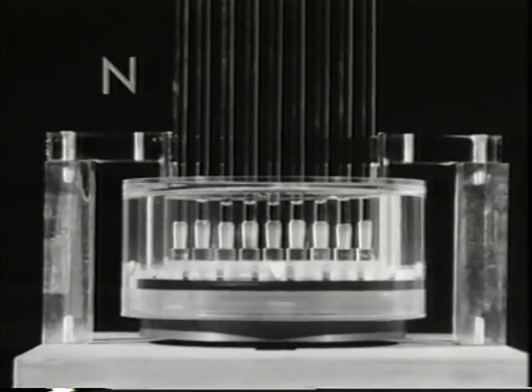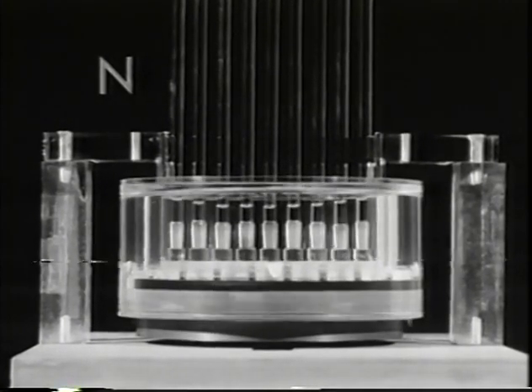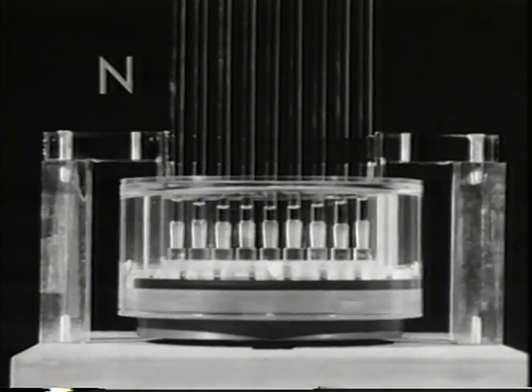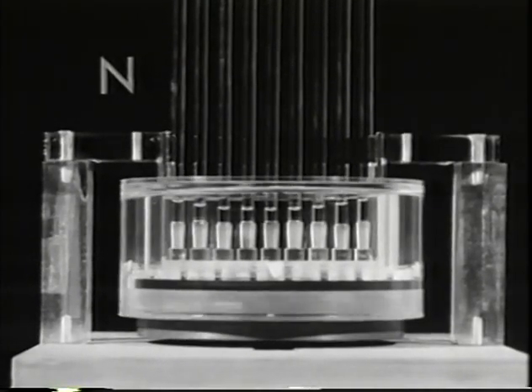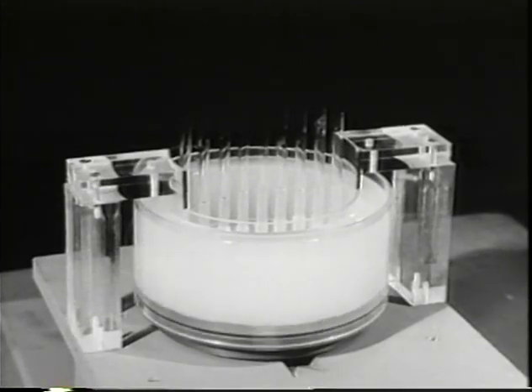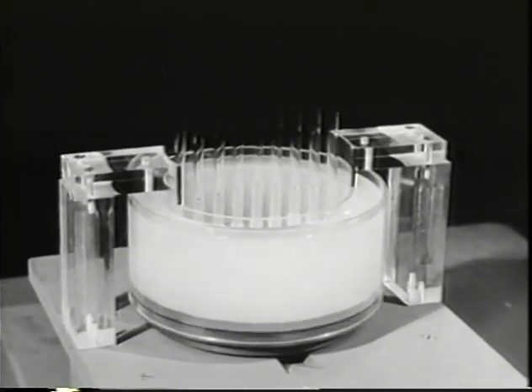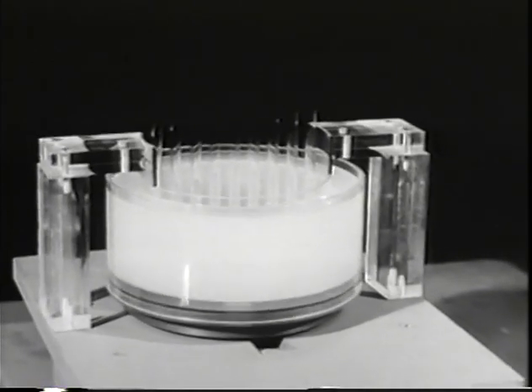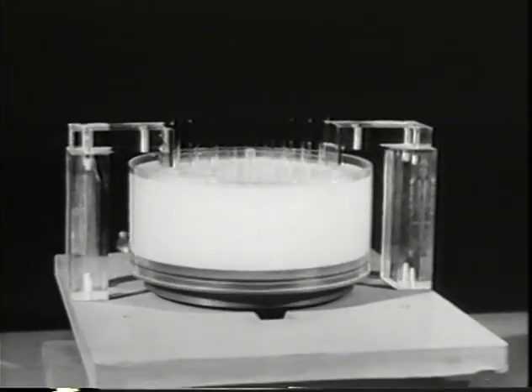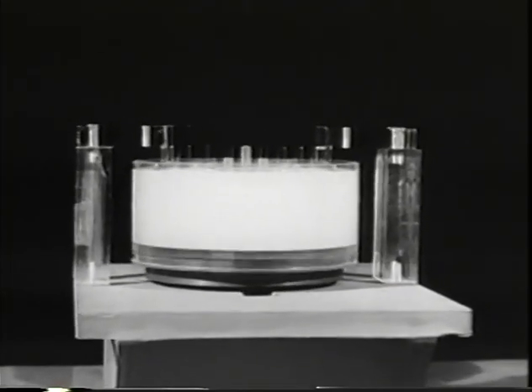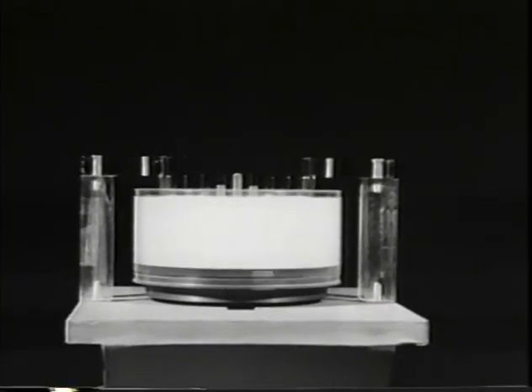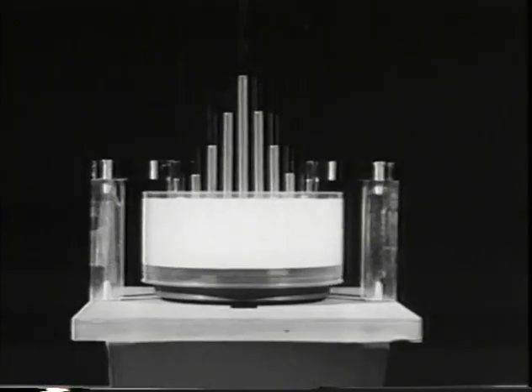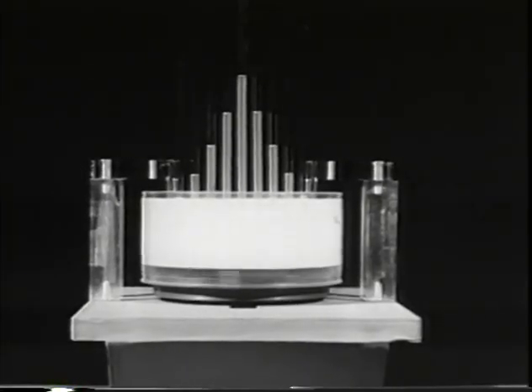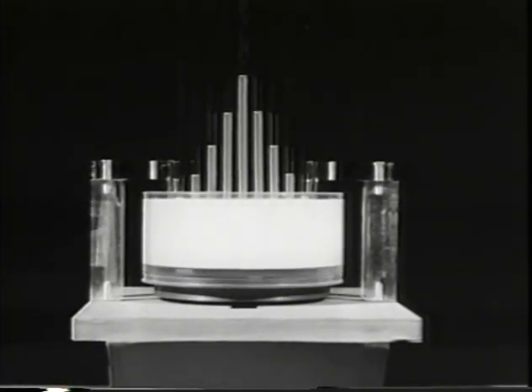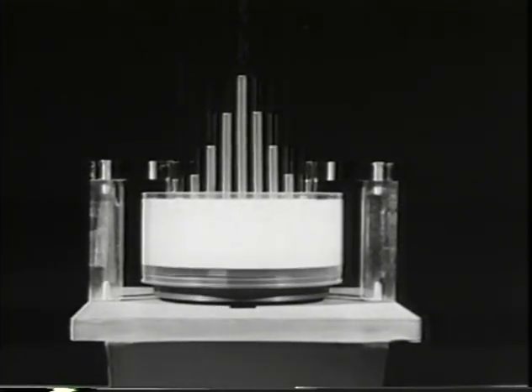If the fluid is Newtonian, the height of the fluid in the tubes at steady state is a little less near the center than toward the outside. For a non-Newtonian fluid at the same speed, the force normal to the stationary plate may be considerably greater toward the center. Although the steady state stress distribution between the plates is attained almost immediately, again it took several hours for the levels in the tubes to reach their final positions. Indeed, quite high stresses can occur near the center, and this principle has been used in the design of a pump for molten plastics.